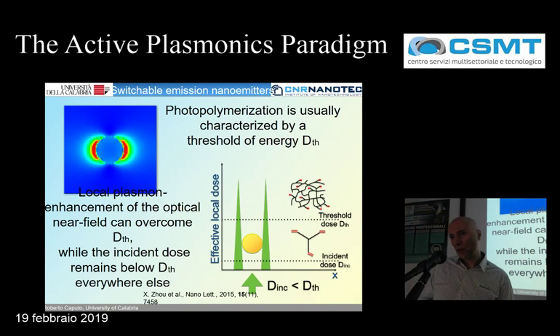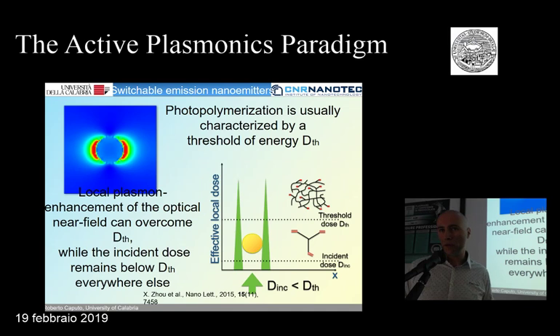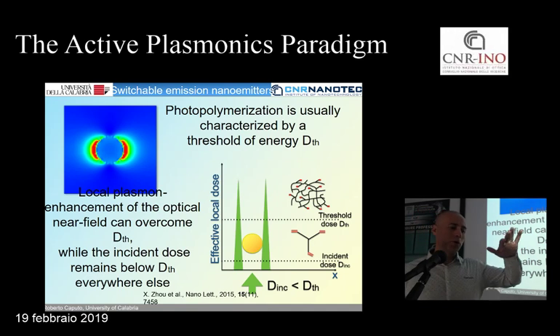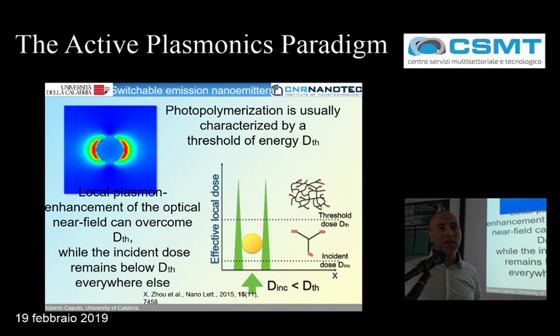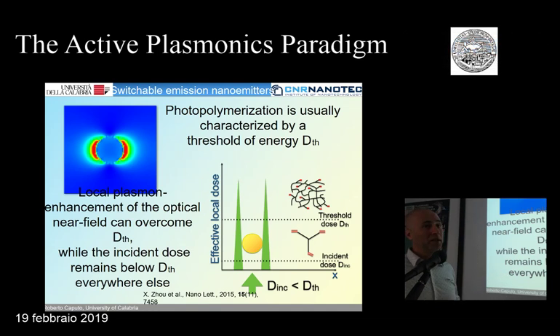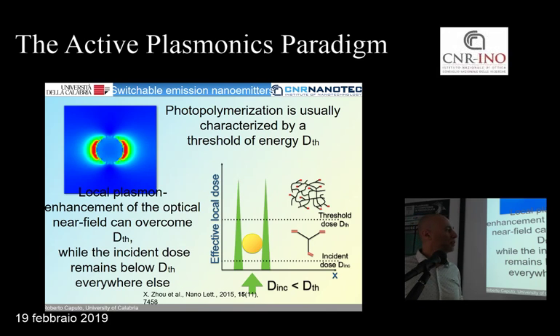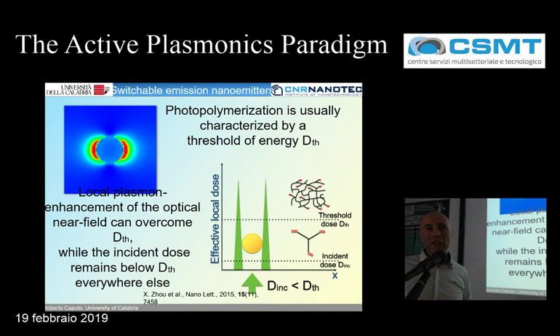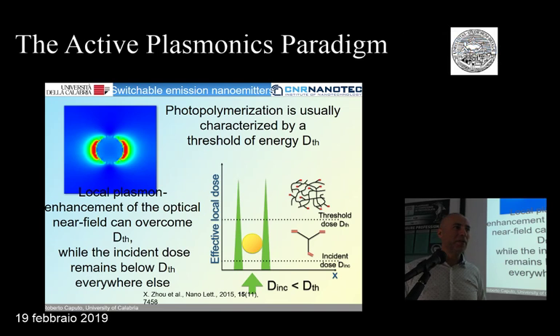As you can see, when you have a dipolar excitation of a nanoparticle, in principle, you obtain very intense fields at the border of the particle. So if you cover this particle with a material which is polymerizable by an electric field, you could create the replica of the field by inducing polymerization only in those areas where the field is very high. So, if your material is under threshold everywhere because the field is typically low, but over threshold in the proximity of the particle, you can create this polymerized replica of the field. So you can, in principle, have a permanent image of the field around the particle.